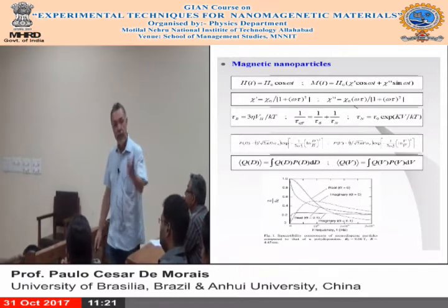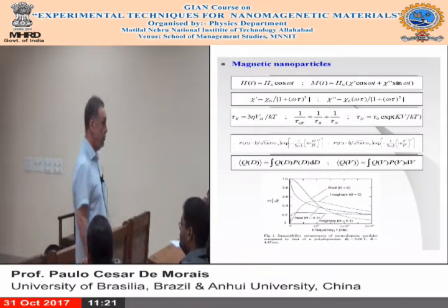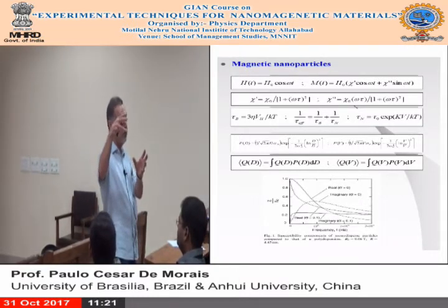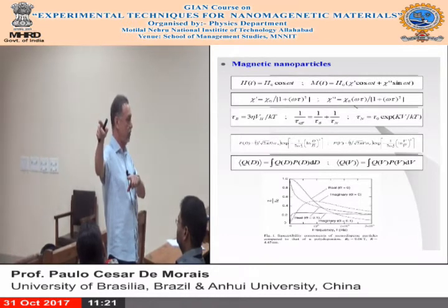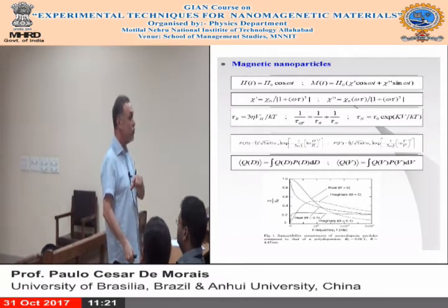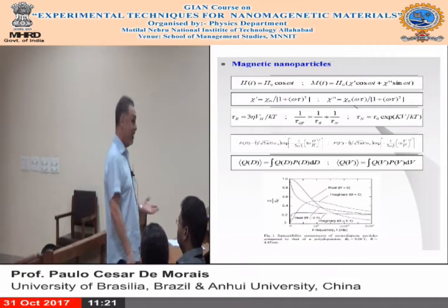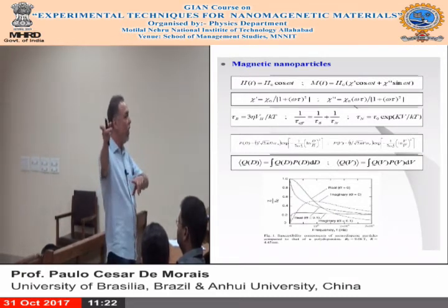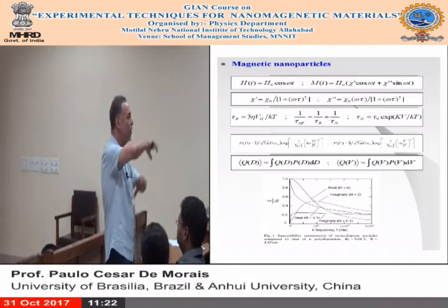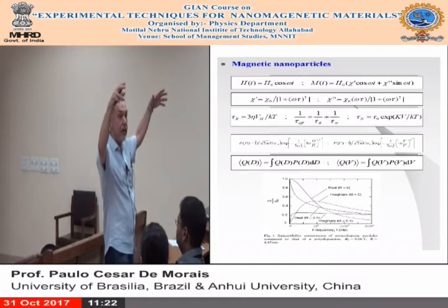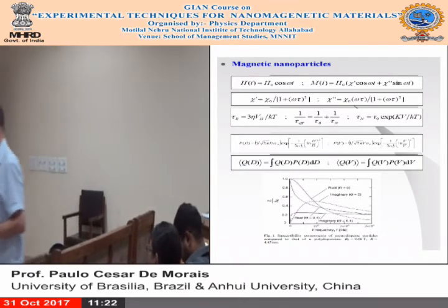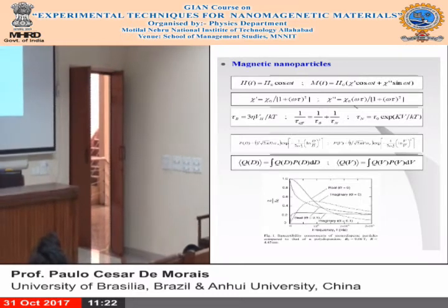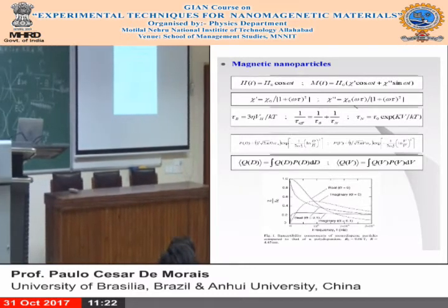See, how do you measure relaxation time in those systems? You measure like this, typically. You apply an external steady field, the field is high, and then you measure the magnetization. And then you switch off the field as quickly as possible. It is not easy. It's a very difficult technical problem. But when you switch off, the magnetic moments start to become random, and then the magnetization drops down. The typical time for dropping down, we call the relaxation time. So, this is a typical experiment.